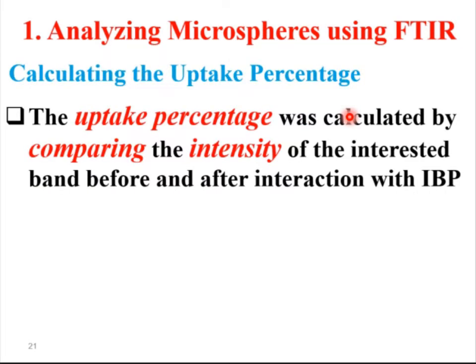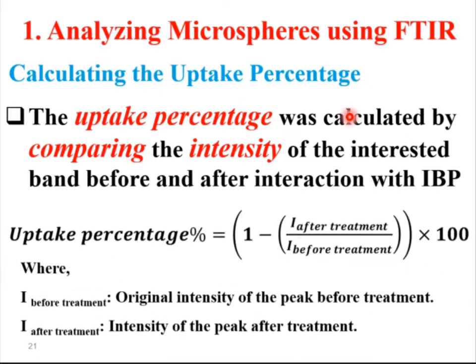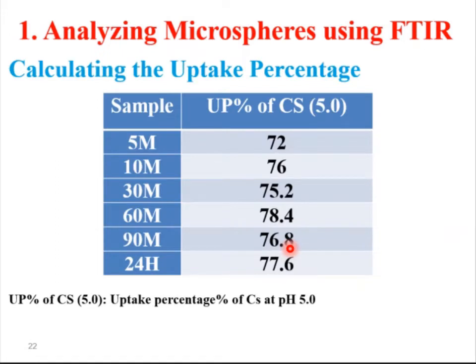Then we use such spectra for calculating the uptake percentage by comparing the intensity of the band of interest in each bending band before and after interaction with ibuprofen using this equation, and the results were that chitosan silica succeeded in removing 72% of ibuprofen during the first 5 minutes, reaching its maximum at 78% after only 60 minutes, stabilizing at 77% after 24 hours.